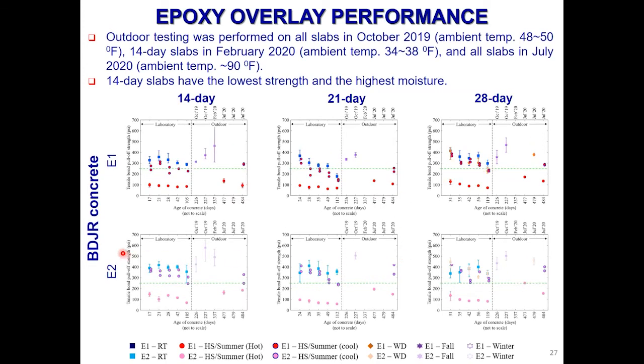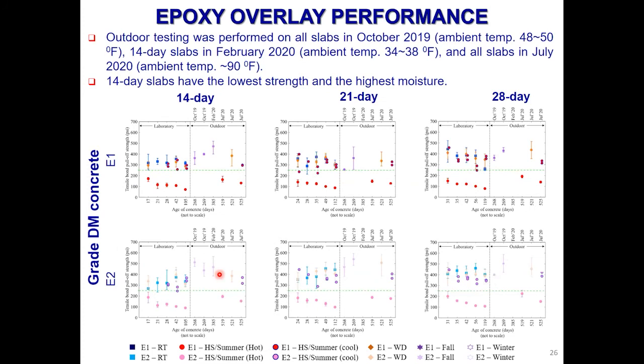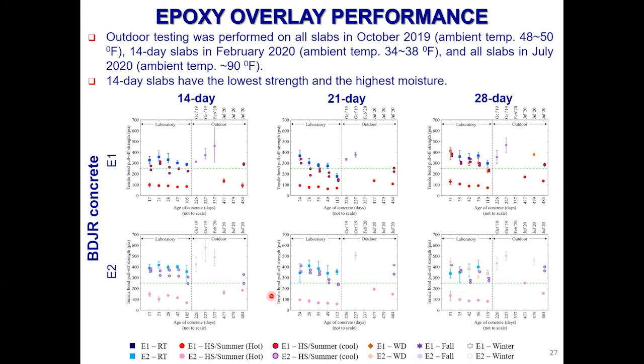And this is when we have type 1 cement, where bond strength is lower than the one with the slag. Okay? But still, we see a little better performance with the epoxy that has little temperature tolerance, as well as low viscosity. So it is easy to apply and helps enhance the interface.